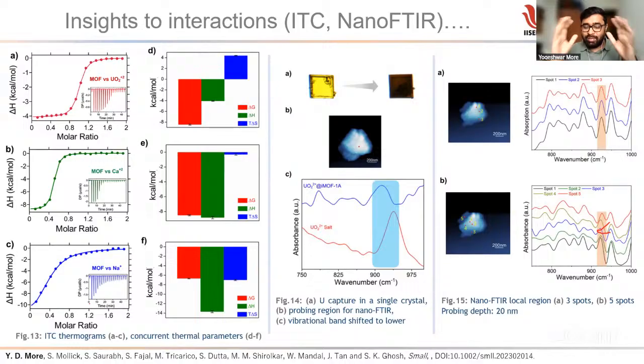So now we need to understand why this is happening. As I have shown you in the first slide, there are DMA cations within the pore channels of the MOF. Once the uranium goes in, it has a +2 charge, that is the uranyl cation. Once it goes into the pore and starts stabilizing interactions with the Lewis basic nitrogen sites, the two DMA cations are now loose from that crystalline assembly, and hence it causes an increase in the entropy. You can see the increase in the entropy, and hence this reaction is favorable.